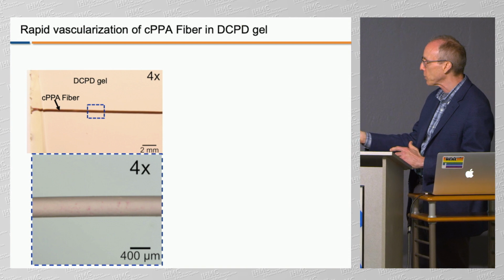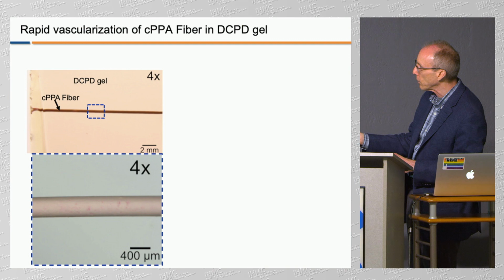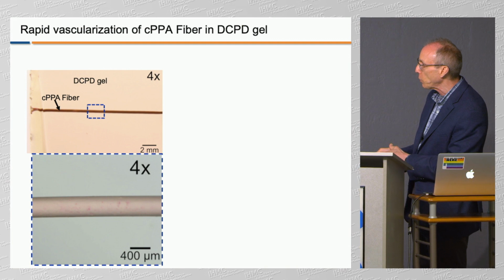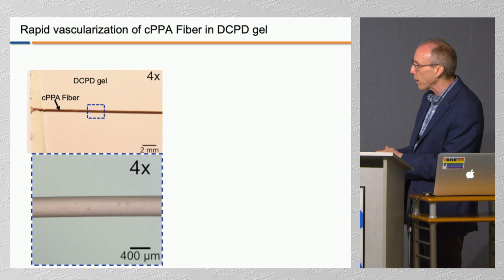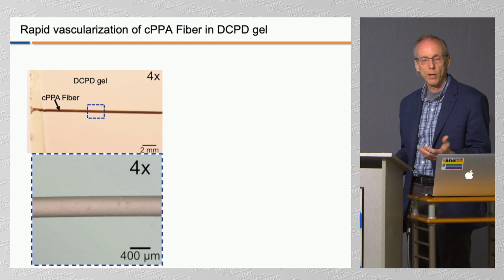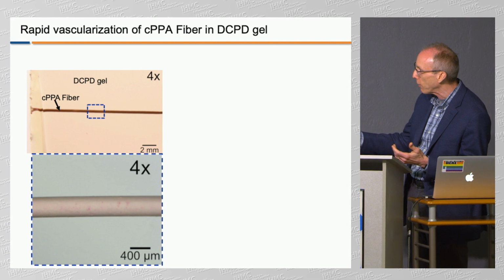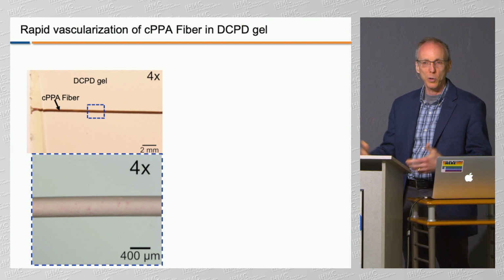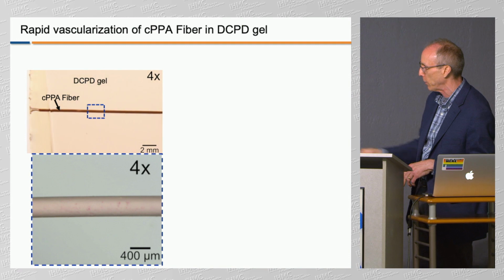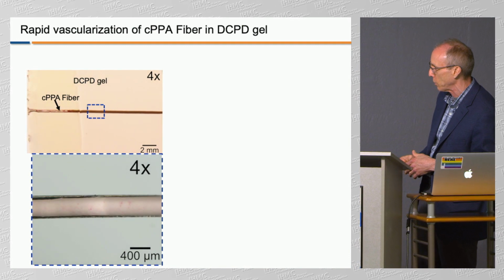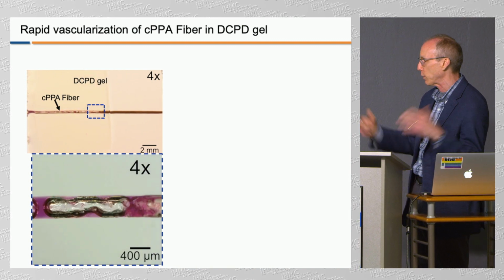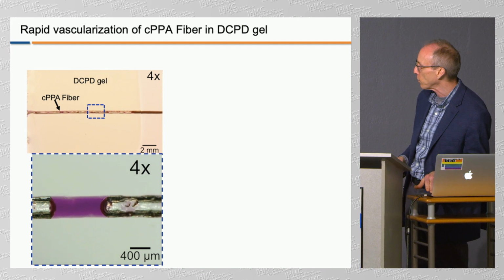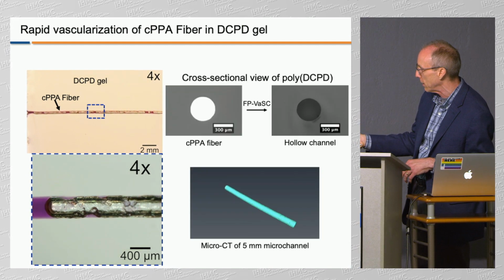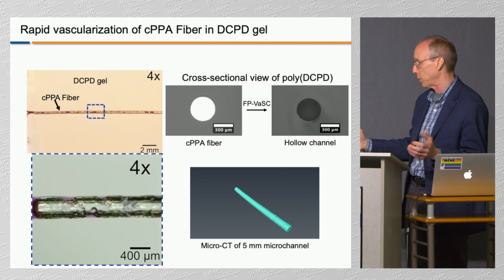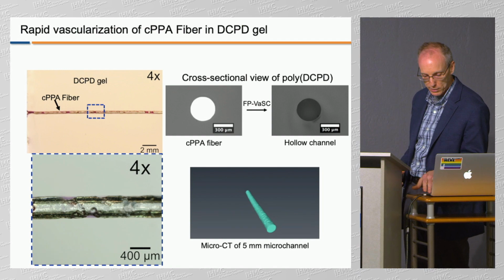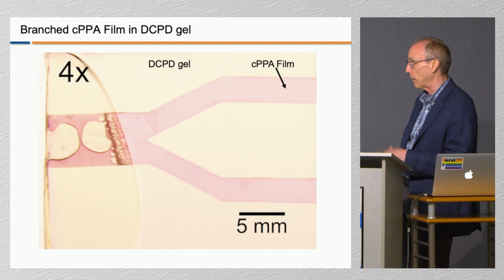So this material depolymerizes, returns to a liquid, and what's going on here is, there's our gel. Remember the gel that you saw Ian do? Here's the front, and the heat from the front is going to transform the CPPA fiber back into monomer, and the monomer that's in the gel is going to be converted into polymer, all with the same heat that was initiated from the very get-go. This is an expansion of the bottom of that blue box. And so you can begin to see something happening. As the front goes through, depolymerization takes place, and a vascular structure is created. There's the channel that was created. This is a negative of that channel, so you can see the structure of the channel is really well controlled, and this is a pretty robust process that we can perform in a variety of different configurations.